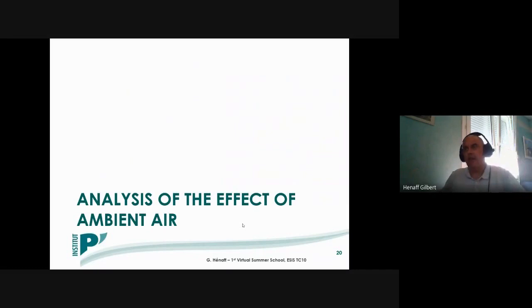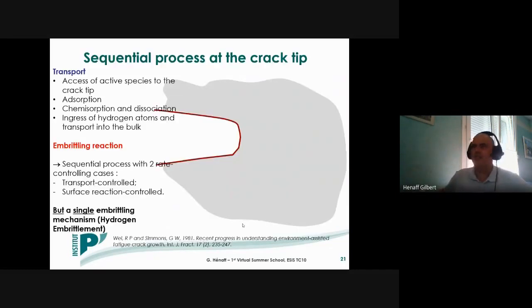So now that we have characterized the intrinsic fatigue crack growth behavior, let me move to the analysis of ambient air. So in literature, this has been addressed, for instance, by Wei and co-workers, and has been described in the form of a sequential process taking place at the crack tip.